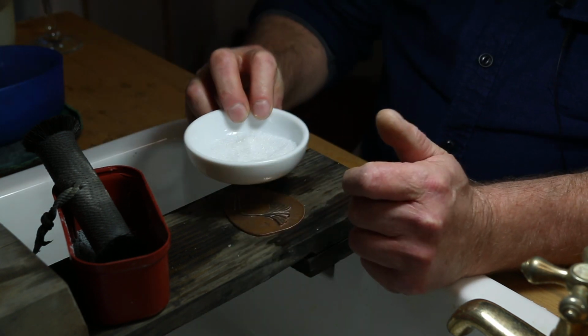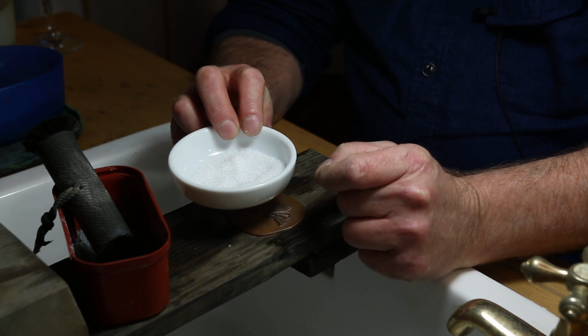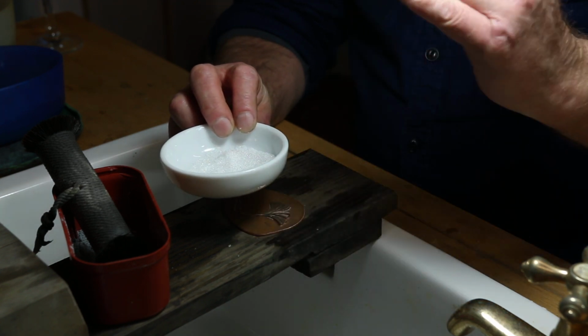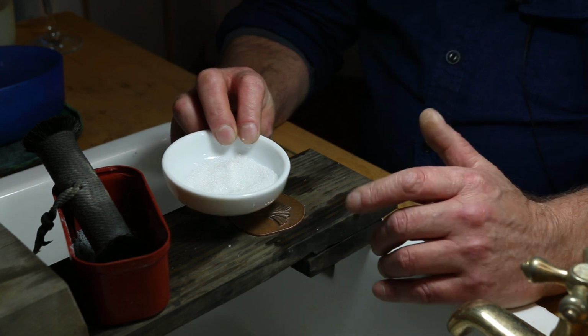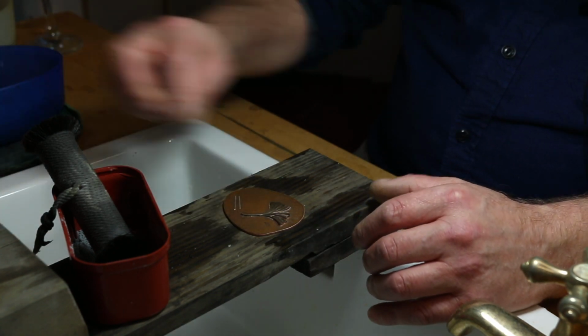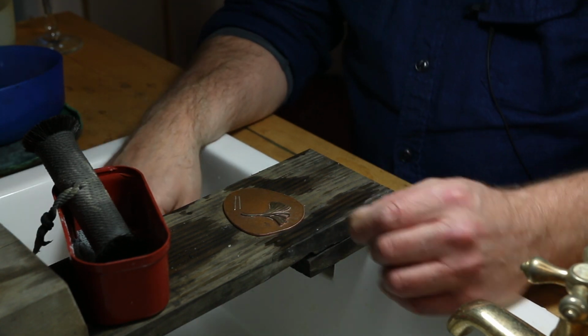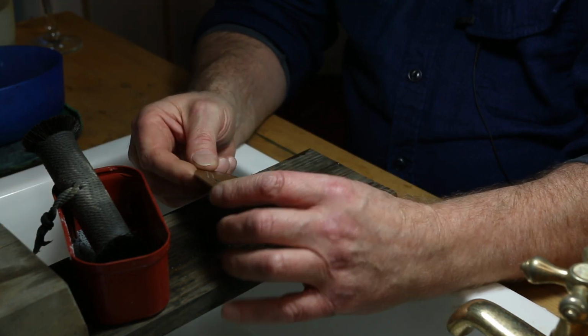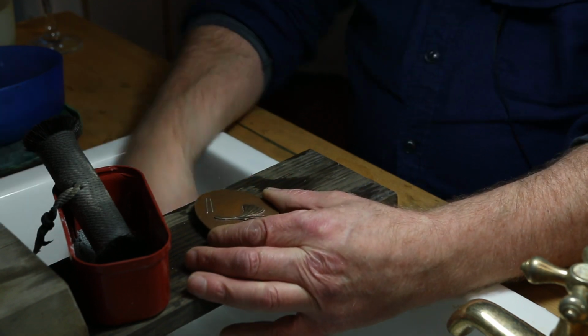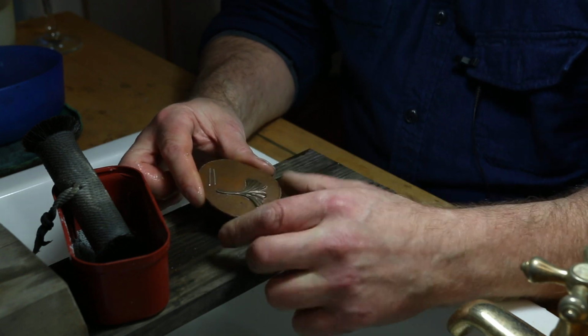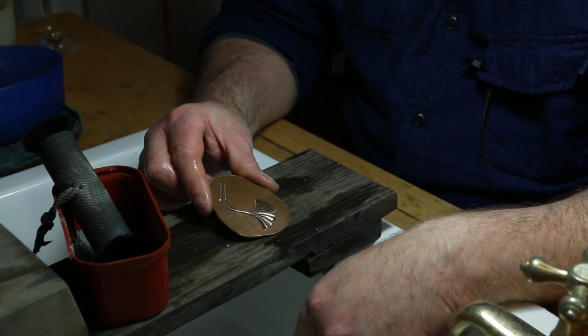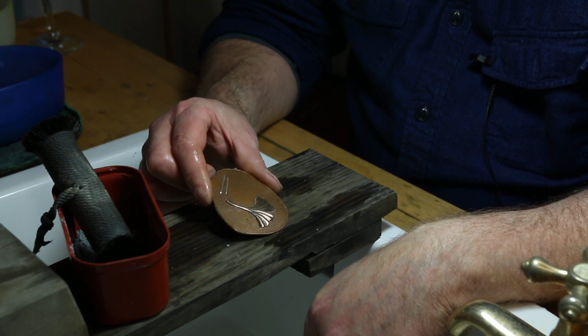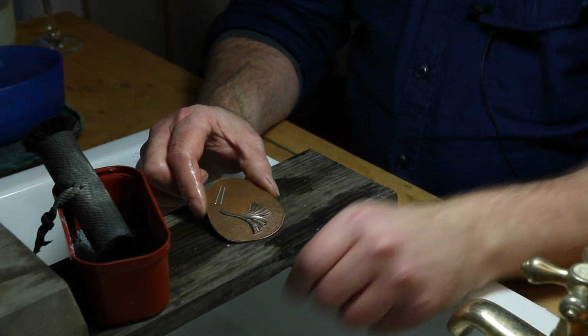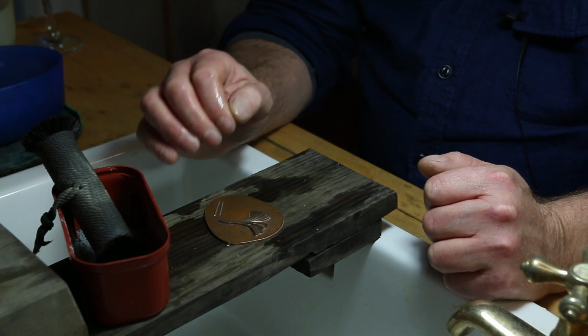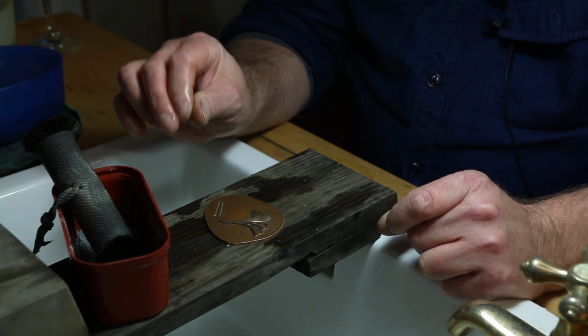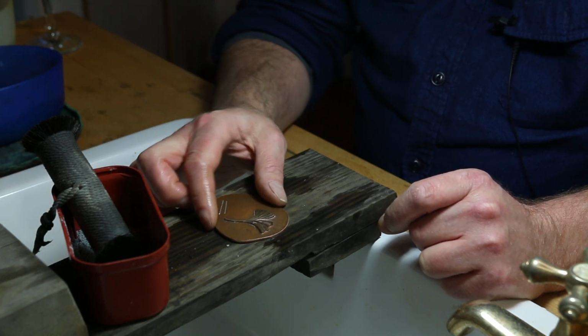This is a deflocculant. What that does is it combines with the chlorides and takes them out of solution, which helps control this tendency of silver and these patterns to develop this yellow tinge. That's the main issue we face with trying to develop good patina. So having been armed with the alum solution, you should be able to at least have a chance of developing a nice clean patina. Be sparing with it though, there's no need to be heavy-handed with any of these processes.